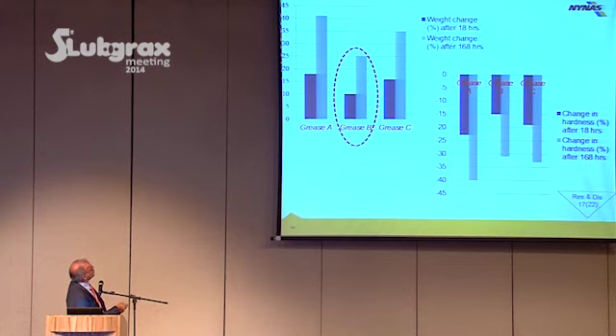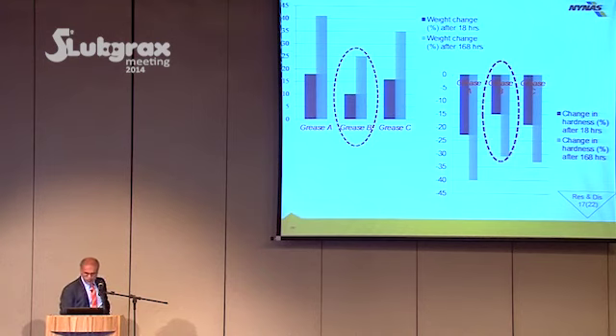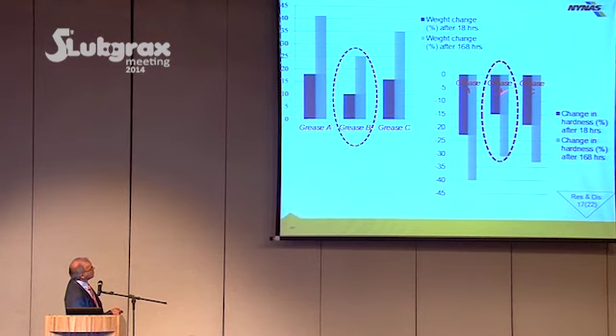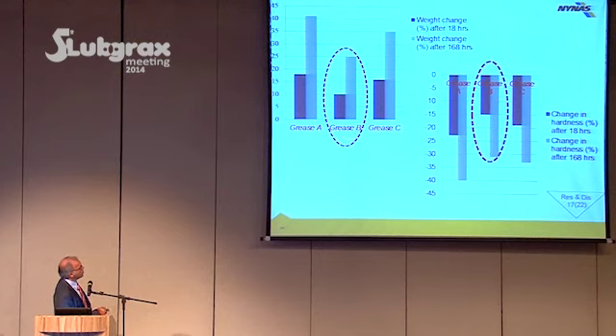Here you have the weight change as a function for those greases. What we can see, first of all, after 18 hours, about 40% of the changes appear. So it is good if you want to screen several greases. You run 18 hours or 24 hours, and then you pick your champion and complete the test. The next slide is for change in hardness. We see that this one, grease B, offers less change in hardness. To us, it's not a surprise, because we have published data in the past where we showed that if you use chloroprene, you have to use an oil with a higher aniline point.